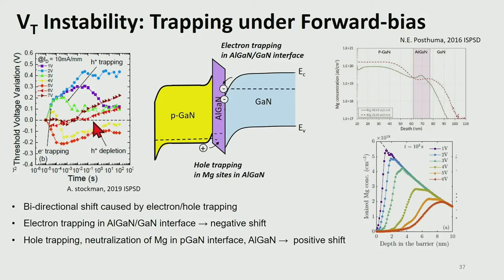In the case of the magnesium dopants, if you grow the P-GaN on top of the AlGaN barrier, the magnesium can diffuse into the AlGaN barrier. So if you do the SIMS measurement after the growth, you can see the magnesium tail in the AlGaN barrier. So magnesium in the AlGaN barrier is activated because of the polarization field in the barrier, and it can cause the more positive VT in the fresh device.